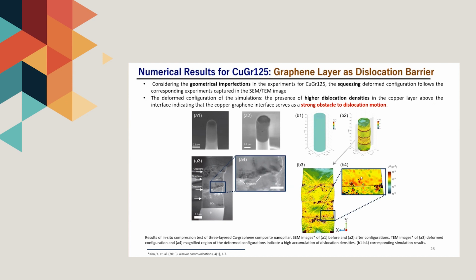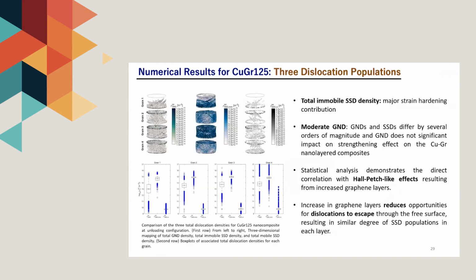As the layer spacing is reduced, the chance of depletion of dislocations through free surfaces is reduced. In this simulation, total immobile SSD density is a major strain hardening contribution. The total GND density does not have a significant impact on the strengthening effect on the copper graphene composites due to the lack of strain gradient on the sample.